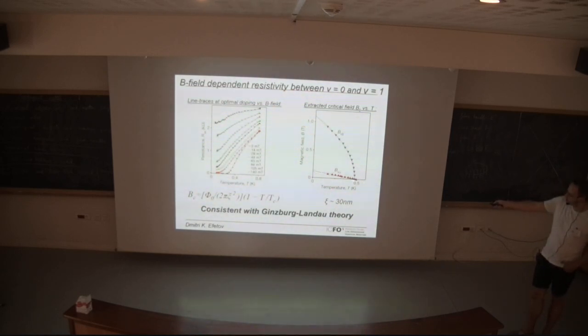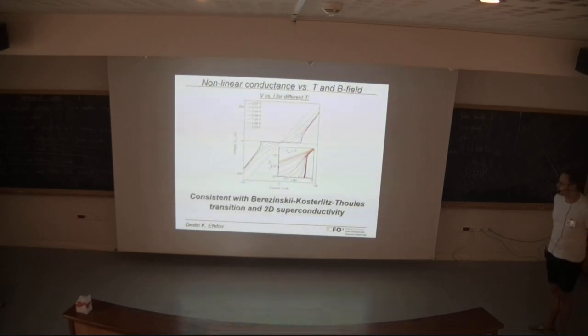from this magnetic field dependence we can extract the coherence length of this state, and we usually find something in the order of 30 nanometers, but I would say it's usually always a few lattice constants of the Moiré, so it's usually 2 or 3 lattice constants. Okay, so that's another evidence that this looks like superconductivity.